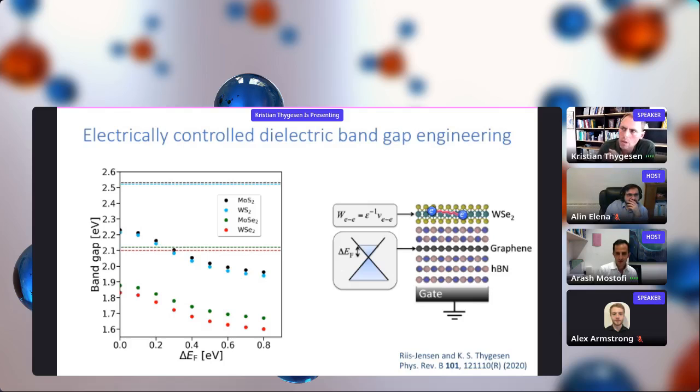I think one of the big challenges now is with these twisted heterostructures, where you can get into regimes where you have these flat bands, where you get highly correlated physics. That's obviously a very quickly moving frontier in the field where there are lots of challenges. These structures are completely beyond what you can reach with full ab initio, because something like the twisted bilayer graphene at the magic angle has about 12,000 atoms in a unit cell.